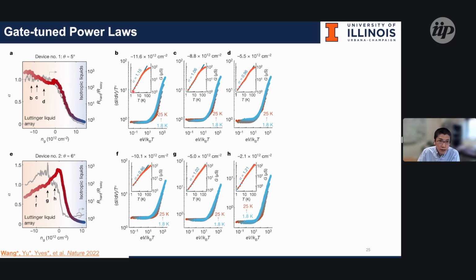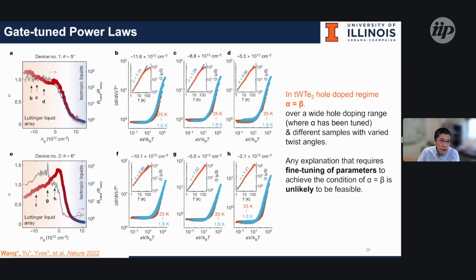The extraction of the power law was done by getting the temperature dependence at low temperature. In the whole doping region, starting from the charge neutrality, the power law is around 1, which indicates a very strong signature of the system. As you dope the density further, the anisotropy drops together with the power law. I want to note that at very low power law numbers, it means the resistivity or conductivity changes by a very small amount. Anything can be fitted with a power law, but this doesn't mean you still have the Luttinger liquid—it's just an indication that the parameter has a significant change from some baseline.